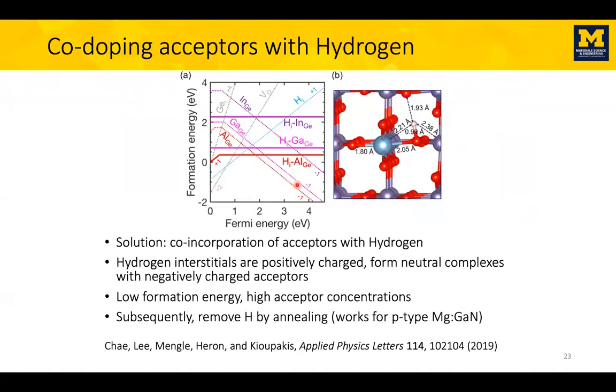However, we found that if you co-dope these defects with hydrogen, what happens is that this interstitial hydrogen will passivate them and create a neutral defect complex. As a result, you can incorporate high concentrations of aluminum or gallium or indium into the lattice, those acceptors, and then you can remove the hydrogen by rapid thermal annealing and get the p-type conduction. So this is a non-equilibrium doping technique. And by the way, this is how it works for p-type doping of gallium nitride with magnesium. That's the work that gave the Nobel Prize to the inventors of the blue LED. So it is possible to p-type dope under non-equilibrium conditions.